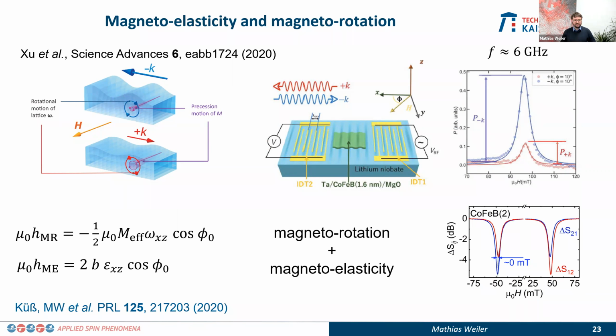And well, basically at the same time, we also published very comparable results on cobalt iron boron, the only difference being the thickness. So we had 2 nanometers, they had 1.6. And we found that indeed, if you look very closely, then the idea that epsilon xz is identical to 0 at the surface is not completely true if your ferromagnetic film is capped. Okay, which it was here and which it also was in our experiments. Typically, you cap to prevent oxidation, and even only half a nanometer of capping will introduce a non-zero epsilon xz. And you can read it up here in this publication.